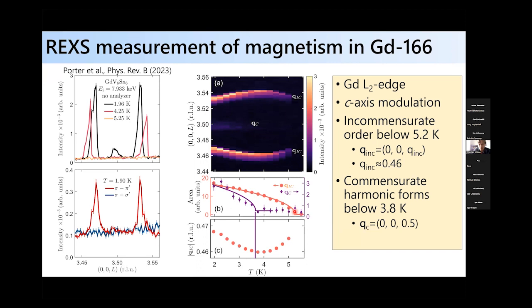If you look at the intensities of these two order parameters as you cool through the ordered state, you can see first the onset of incommensurate order with a sliding Q associated with it. And then at low temperature, at this second-stage transition, you see the commensurate harmonic turning on.